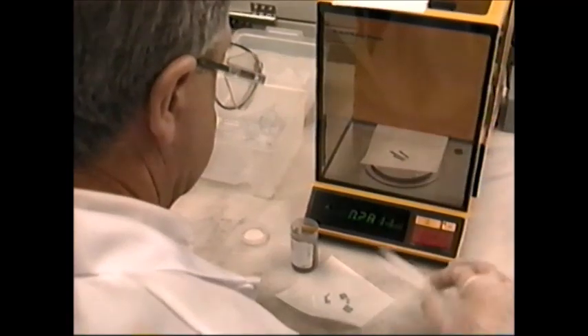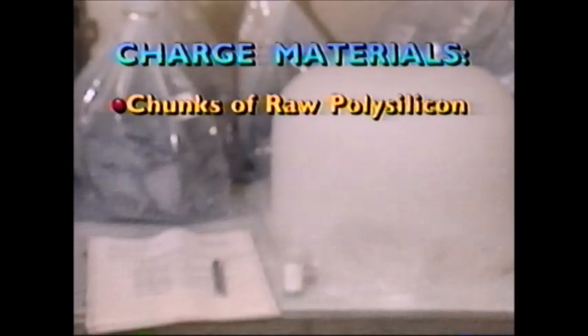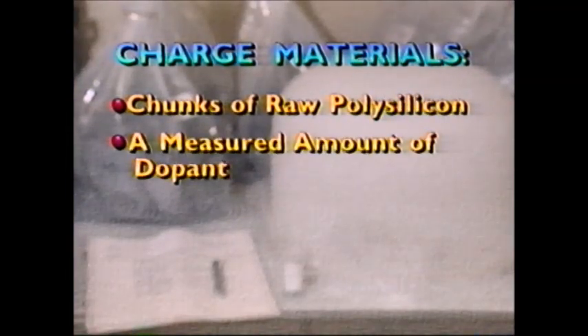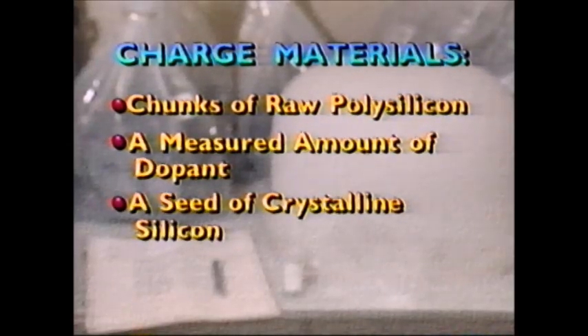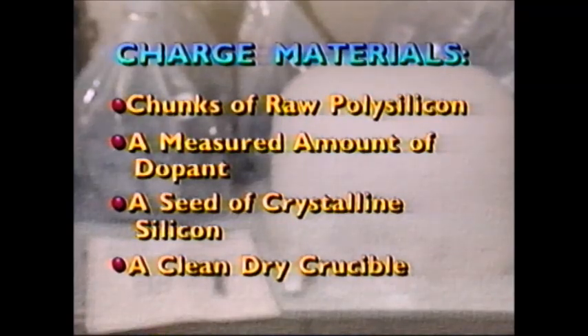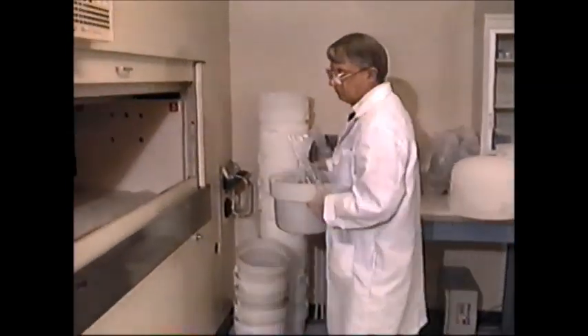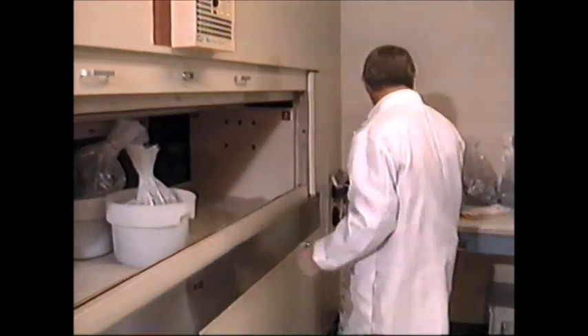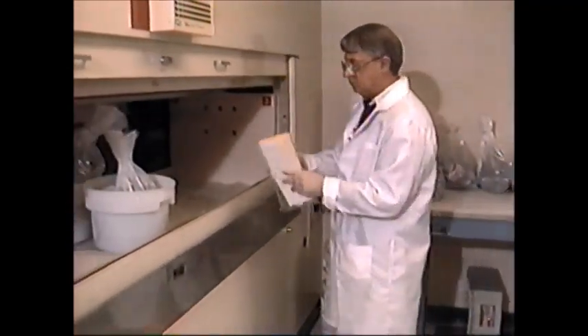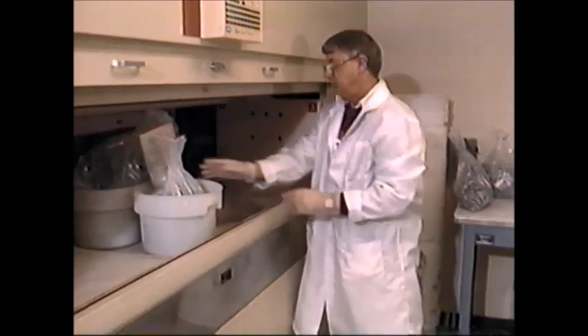All details concerning each charge are recorded on a computer printout, referred to as a traveler. The charge is made from chunks of raw polysilicon, a measured amount of dopant, such as pure boron or phosphorus alloy, a seed of crystalline silicon to determine the crystal structure of the finished ingot, and this is used to start the crystal growth at a particular orientation, and a clean, dry crucible. The size of the load and crucible depends upon the size of the crystal ingot to be grown. After preparation, the charge is taken to the crystal growing furnace.